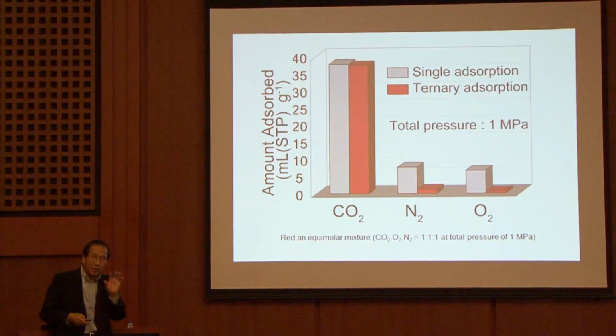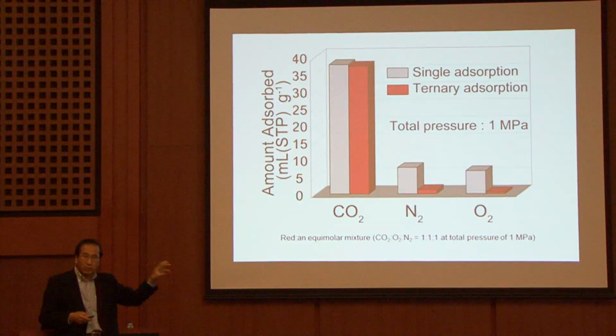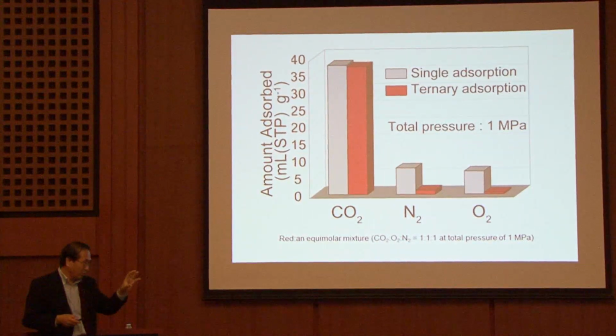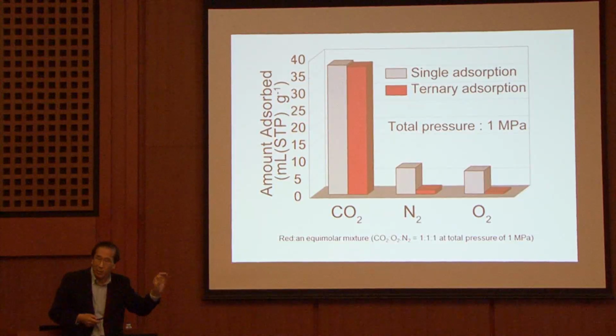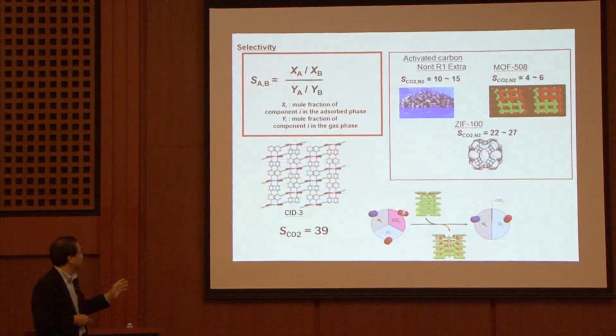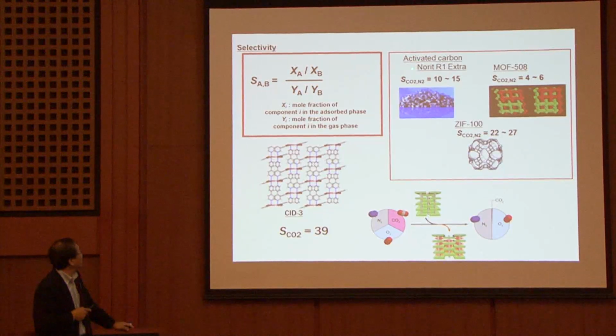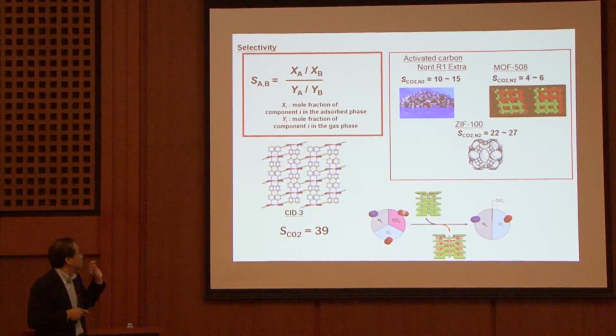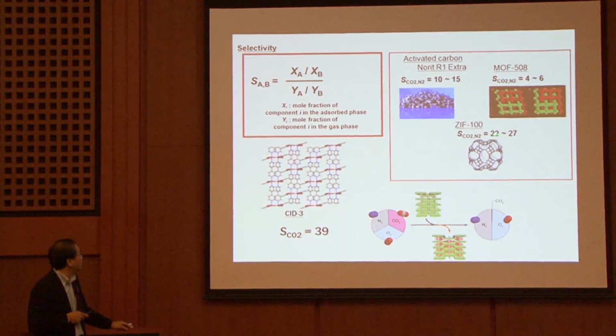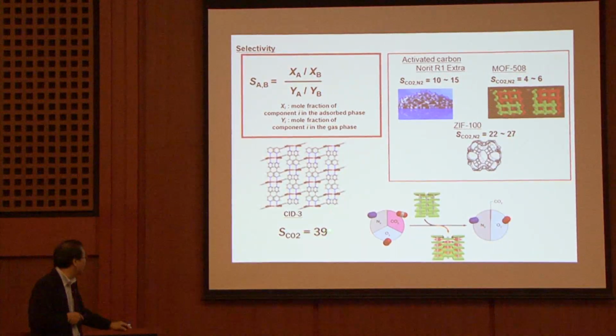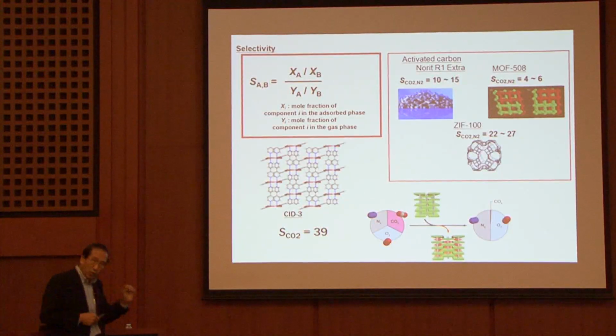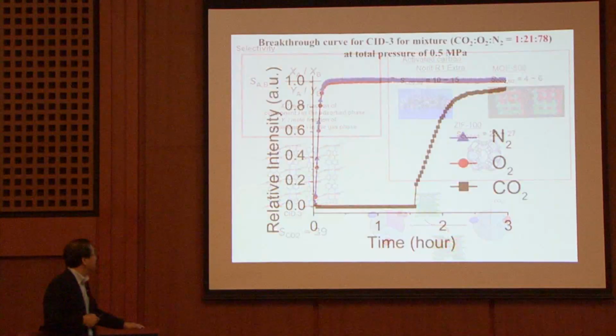Maybe this has a kind of flexibility. So like my hand, this molecule, this framework can trap the CO2 preferentially, maybe. Still missing, but anyway, in the case of activated carbon, the selectivity is 10 to 15. In the case of a rigid, robust framework, a MOF or metal organic framework, it is 4 to 6. And the highest one is 22 to 27. Our case is 39. We can increase more. So flexibility is very important.